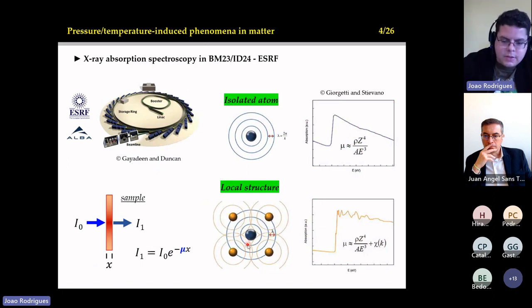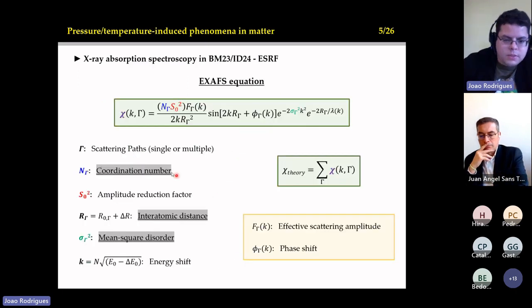In this case, let's say this is cobalt, we have 4 oxygens around. You can determine this quite precisely. You can also determine the distance between the target atom and the neighbor, and also the disorder parameter. The disorder parameter was very important for us. I will show later.